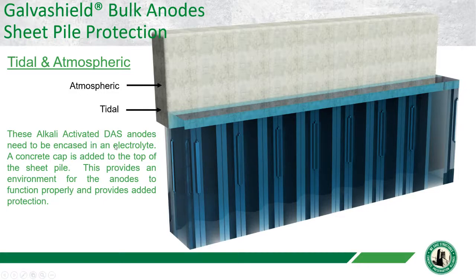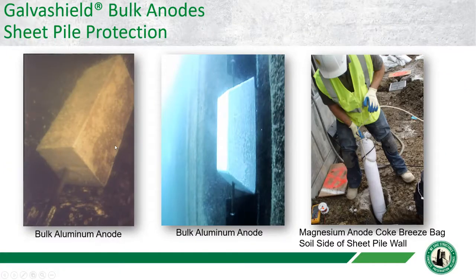So here's just some pictures of some of the aluminum bulk anodes that are welded or applied to the sheet pile wall. It's obviously hard to get these pictures. It's hard enough to get pictures from a construction site, let alone underwater. So you just see the bulk anode here. It's just directly welded to the sheet pile wall. On the right side, I'm sure some people would be familiar with this type of anode, but it's actually a magnesium anode here.